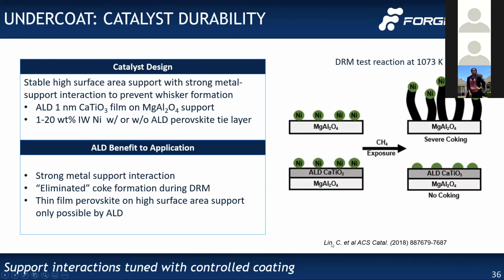This is a paper from Pennsylvania State University. It has a calcium titanate ALD layer and nickel deposited by incipient wetness, same nickel deposition on both, just with an ALD layer added. The ALD, when exposed to methane, did not have the carbon nanotube or carbon whisker formation that a standard catalyst in dry reforming of methane will have, where the nickel is actually pushed off the surface and reacts so much that it fills up the reactor with carbon nanotubes or whiskers, plugging the reactor.